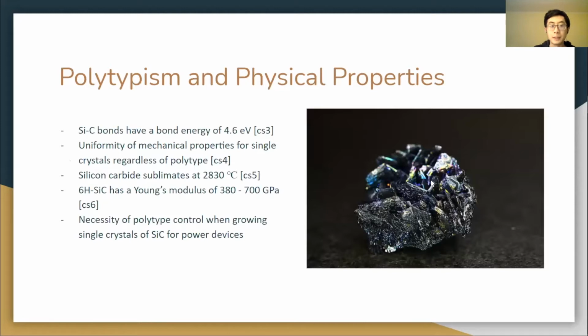How does the polytypism of silicon carbide affect its physical properties? Across all polytypes, mechanical properties are nearly identical. All polytypes, regardless of crystal structure, feature a network of covalently bonded silicon and carbon atoms. These bonds have an extremely high bond energy of 4.6 electron volts, giving rise to silicon carbide's unique thermal and mechanical properties. To list a few, silicon carbide does not melt and instead sublimates at 2830 degrees Celsius, is very chemically stable, and is one of the hardest materials on the planet.